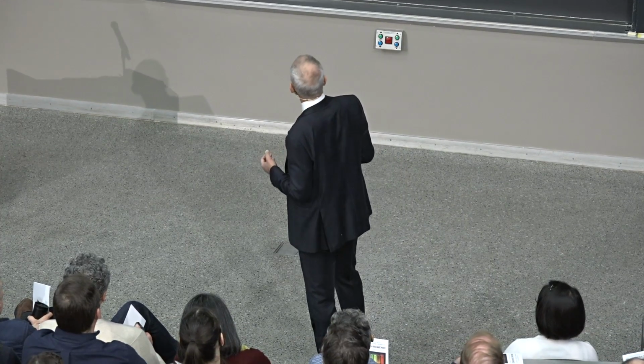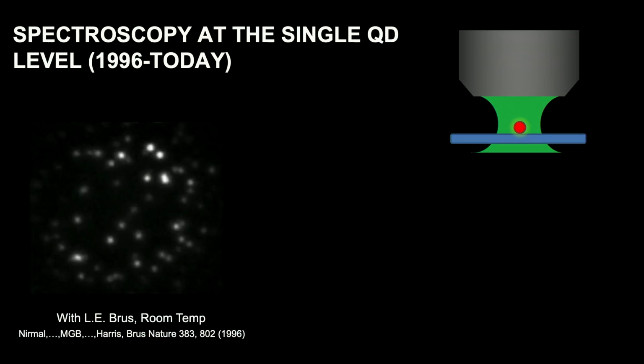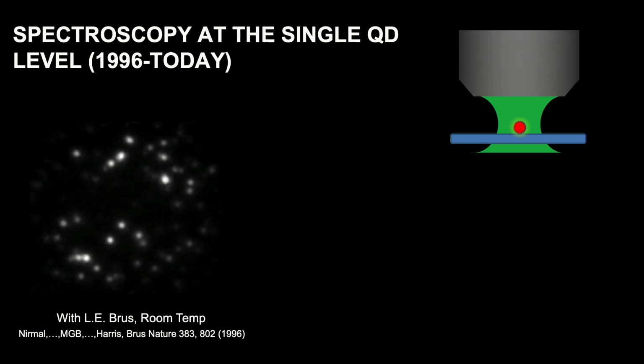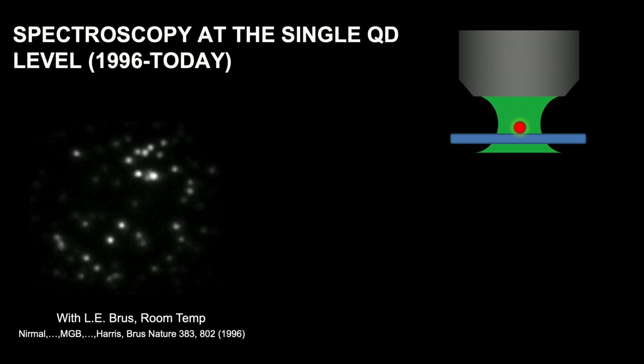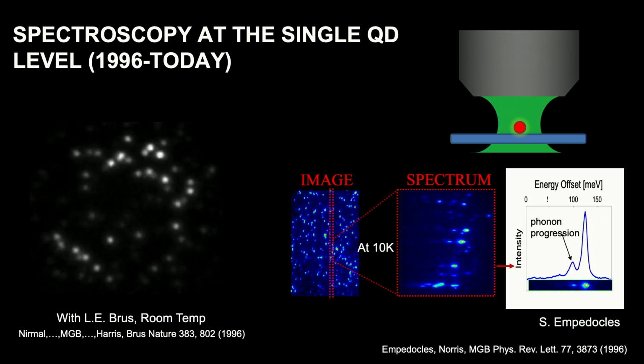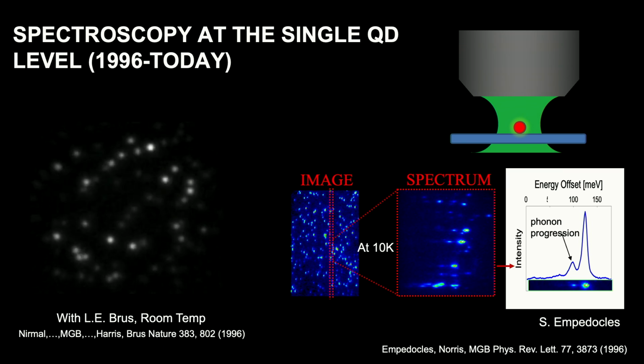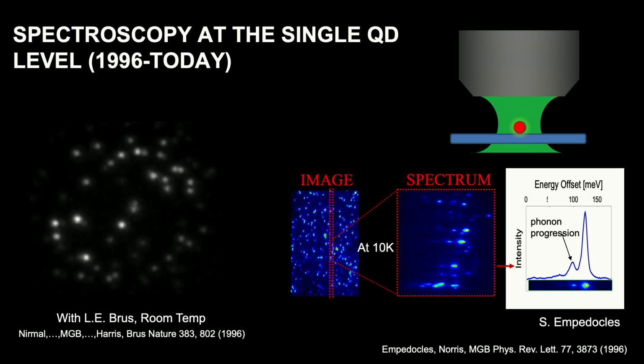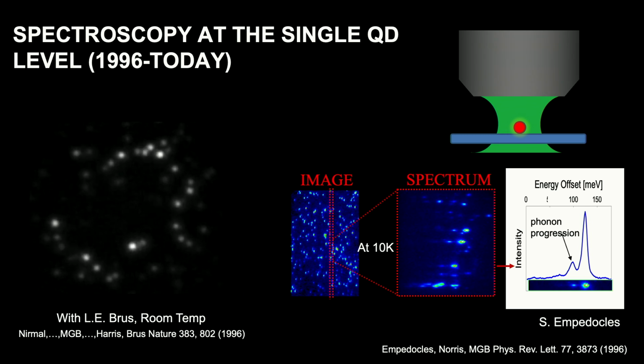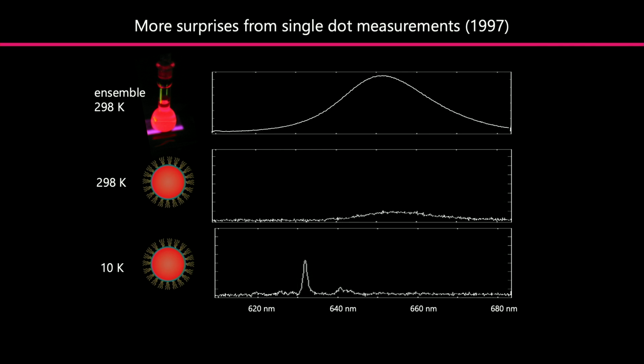And so we started doing that, and what we find is that they're really not that stable. There's interesting things going on. So you could say, okay, this is trash, or you could say, wow, there's interesting physics going on here, right? So they blink on and off, and when you go to low temperature, at liquid helium temperature at 10 Kelvin, then suddenly you can see that this fundamental absorption suddenly gets really narrow in energy, and then you can start to see what we call phonons, which are basically vibrations of the particle. So you can begin to understand how that electron is coupling to the motions of the atom and how strongly that coupling is happening. So this was 1996, and we're still doing single quantum dot spectroscopy today.